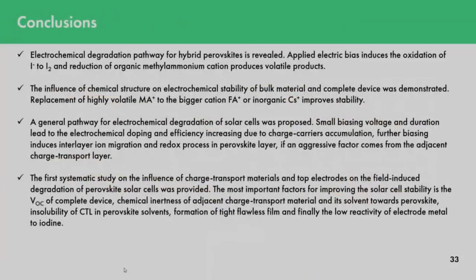So according to everything mentioned here, we can make several conclusions. Electrochemical degradation: we proposed the electrochemical degradation pathway for hybrid perovskites, and we think that applied electric bias induces a redox reaction, which includes oxidation of iodine anions into molecular iodine and reduction of the organic methylammonium cation in this case, producing volatile products.